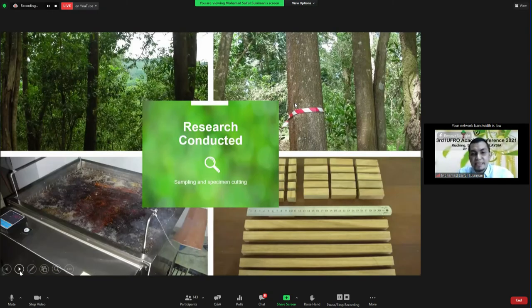All right, so this is illustrated in four figures on the slide. They represent our research from the field to the laboratory test. The first and second figures indicate the random samples selected of acacia hybrids in the field of study. The third figure shows the thermal treatment with palm oil as the medium for the curing treatments, and the temperatures and durations are monitored using the control panel of the machine itself. The last figure highlights that the sample cutting follows the ISO standards before our testing of physical and mechanical properties is conducted.